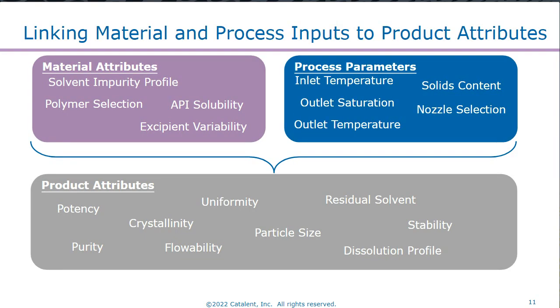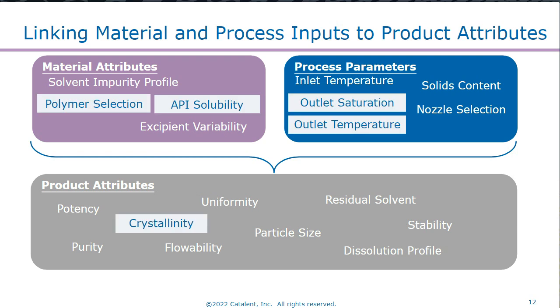Another way to think about this is the links between your material attributes and your process parameters and how those will affect the product attributes of your material. Formulators and process engineers should have a mental map of the way that the variations in these inputs will change the outputs of your product. A good example is crystallinity. For spray-dried dispersion, we often want to ensure that the API is completely amorphous. This can be controlled by understanding your polymer selection and the API solubility in your solvent blend for your material attributes. And then critical process parameters are going to be things that control the kinetics of drying, which are often summarized as the outlet saturation and the outlet temperature.